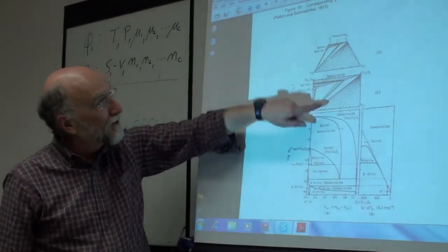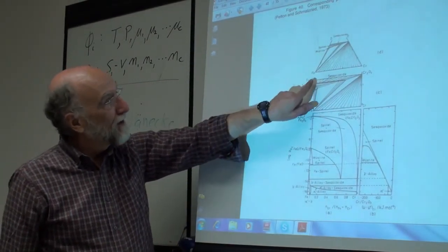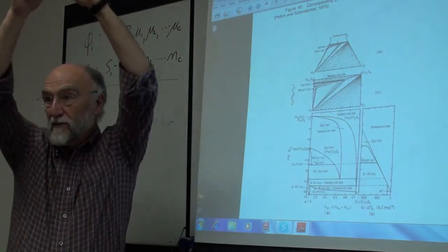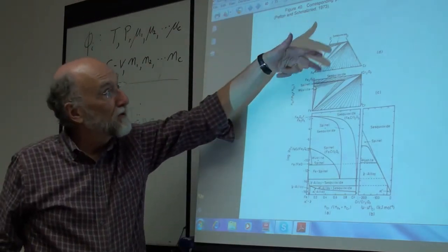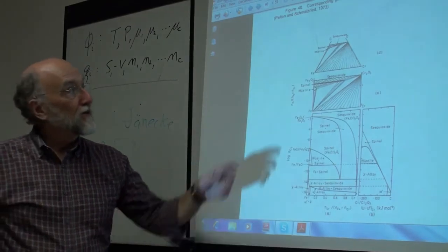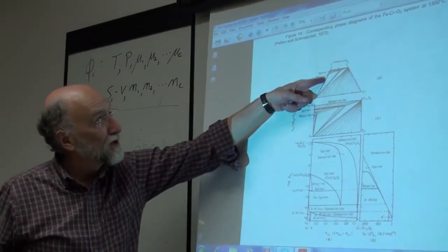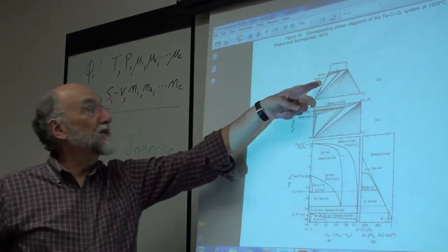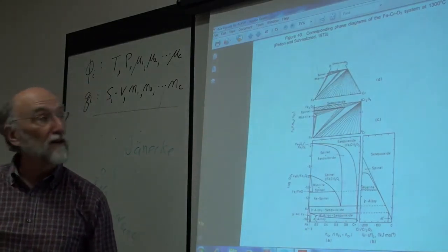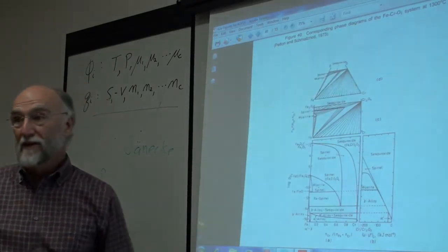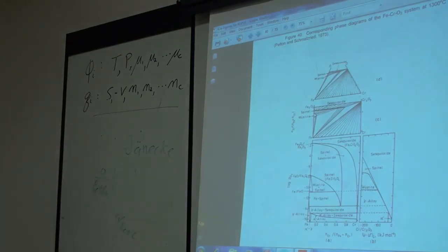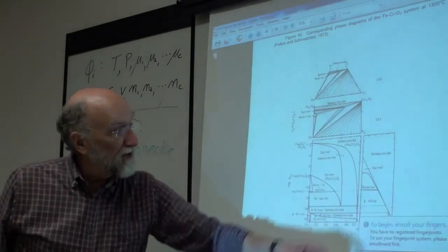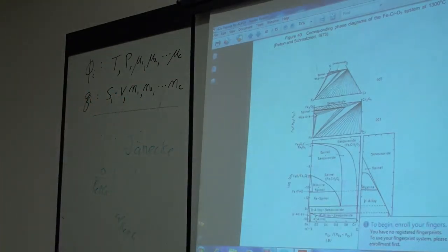So this is just a coordinate mapping. You're remapping the coordinates. Here I've taken the iron-chrome ratio and I've just folded up the top to put the oxygen up. This is just a coordinate remapping of that system. So you see that this is basically a corresponding diagram to this. This is your classical isothermal section of the iron-chrome-oxygen diagram, where you have one-phase, two-phase, three-phase regions. They're corresponding diagrams, so these diagrams are complementary and give you a whole bunch of information.